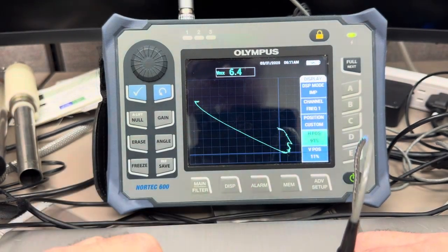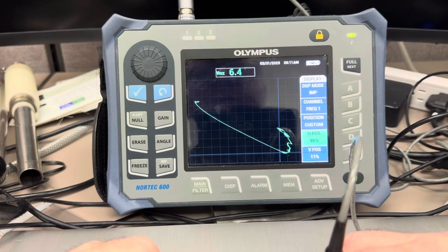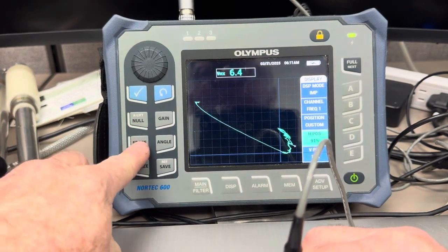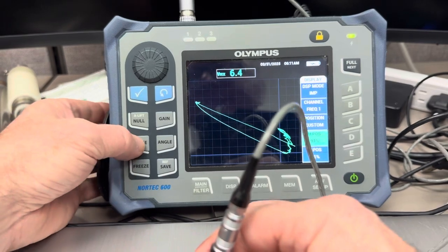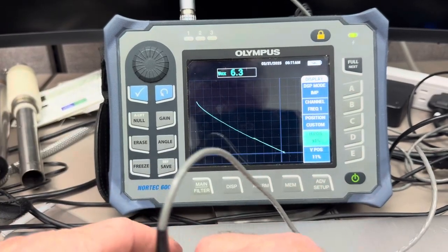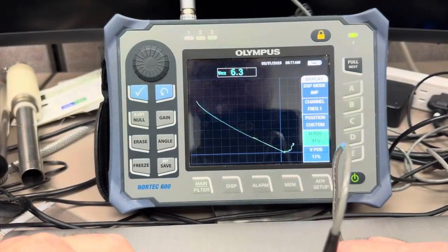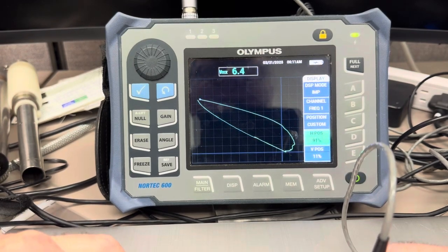That's a little bit of liftoff, the most troublesome variable in eddy current testing. That's why that line started jagged. Let's just erase and start over because I don't like messy. There's a liftoff line scrolling down the material, and you're going to hear it click when I fall off the thin end. Click, see? So that's my thinning curve.